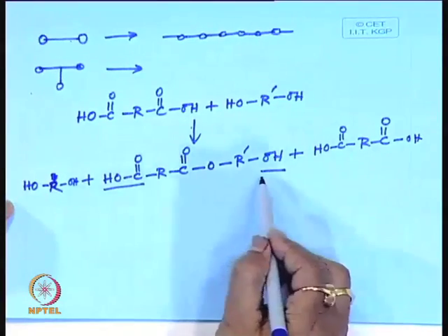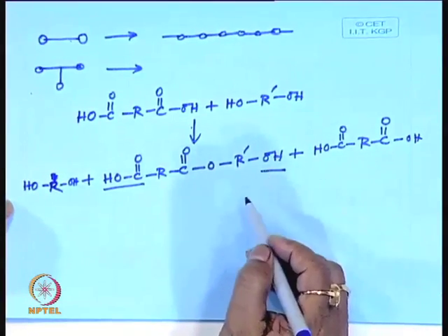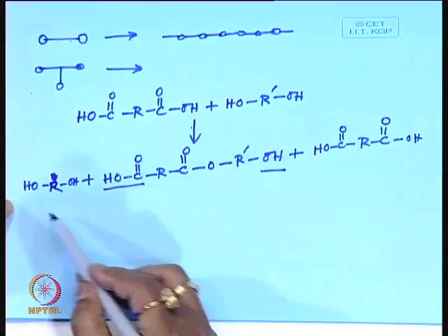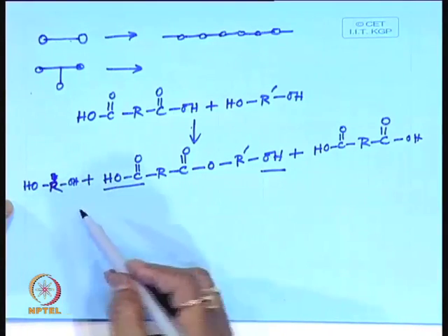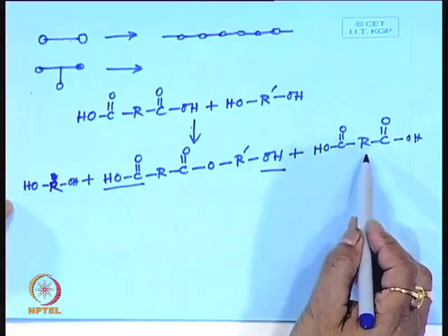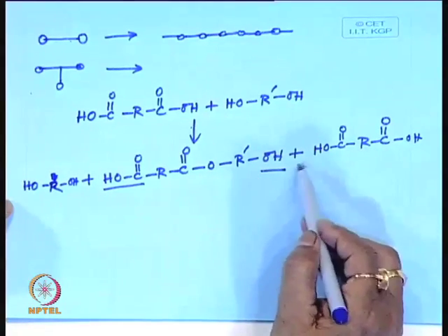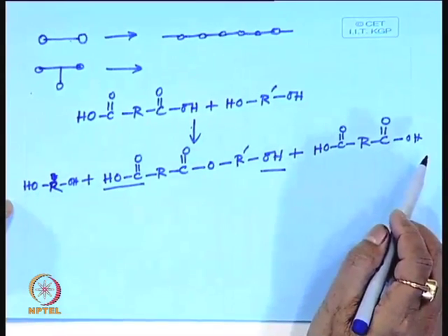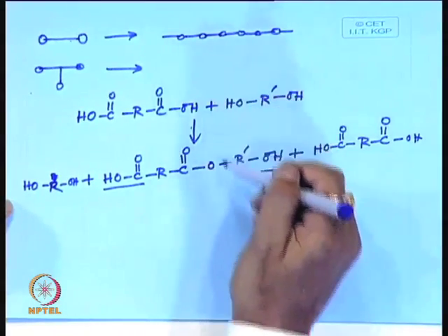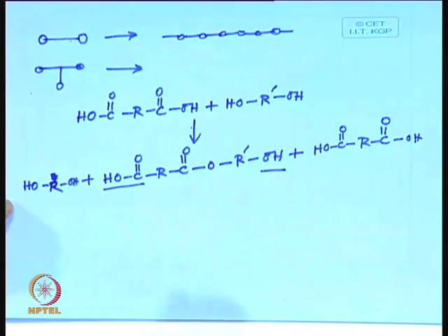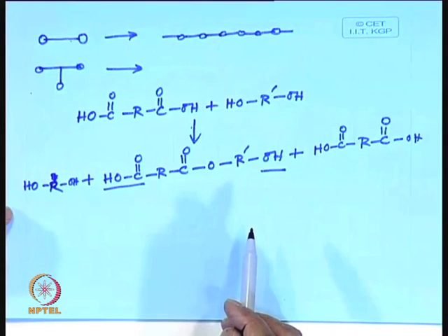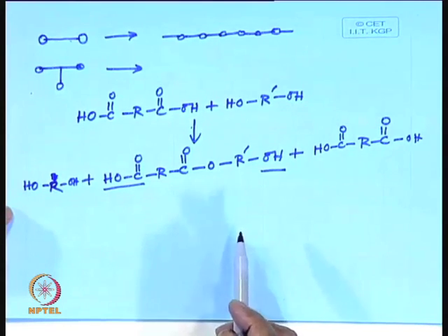So, this intermediate has a capability of reacting with one diol molecule at one side, one diacid molecule on the other side. So, this way it will continue to go on increasing the length, and these reactions occur in so many different steps. And you know, these esterification reactions or amidification reactions are all equilibrium type reactions. They reach an equilibrium after certain progress.